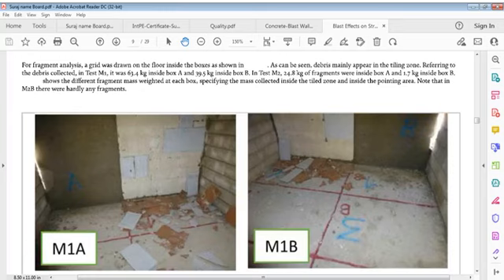So here we can say, as can be seen, debris mainly appear in tiling zone, referring to debris collected in test M1. It was 65.4 kg inside box A and 39.5 inside box B. In test M2, 24.8 kg of fragments were inside box A and 1.7 inside box B.